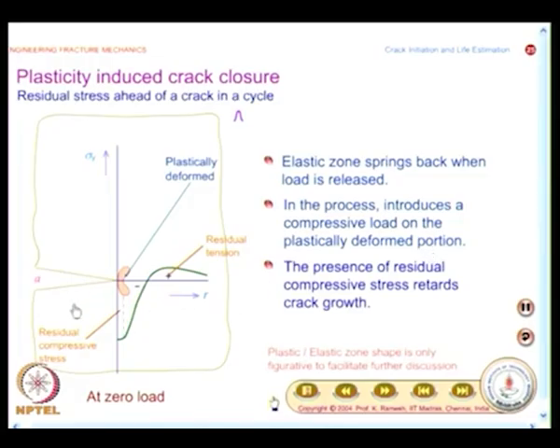So, you will have a residual compressive stress and a residual tension. If you understand this, many other discussions, what happens when there is an overload, what happens if there is a crack closure, for all of this you have to recognize that because the load is increased and decreased, you have a residual stress formed ahead of the crack tip. This is the first knowledge you should get.